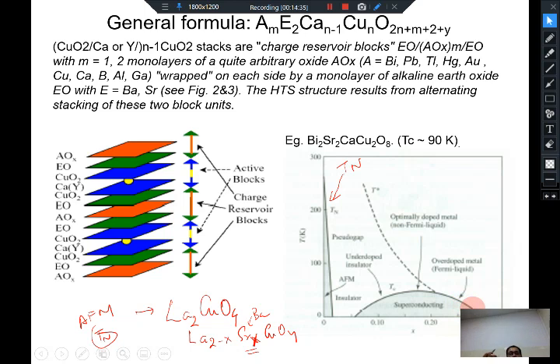So this is the typical characteristic phase diagram of temperature versus doping that you will see in high temperature superconductors. It begins as an antiferromagnetic insulator, you suppress the long range antiferromagnetic order and you get a strange metallic phase, and then there is a superconducting dome. This is called the superconducting dome, and this is characteristic of all high Tc superconductors.